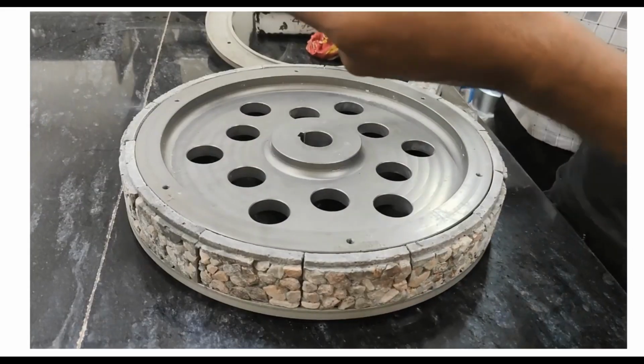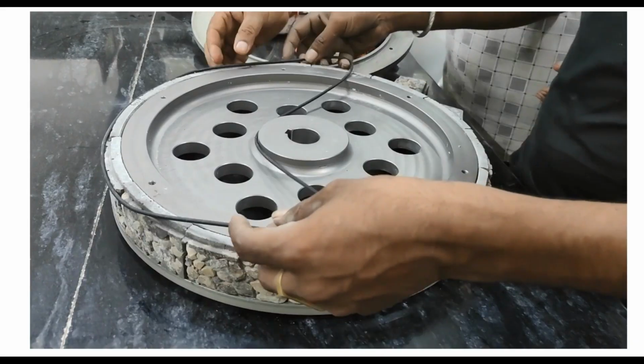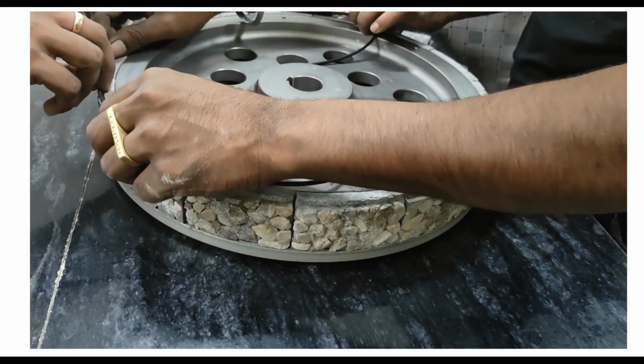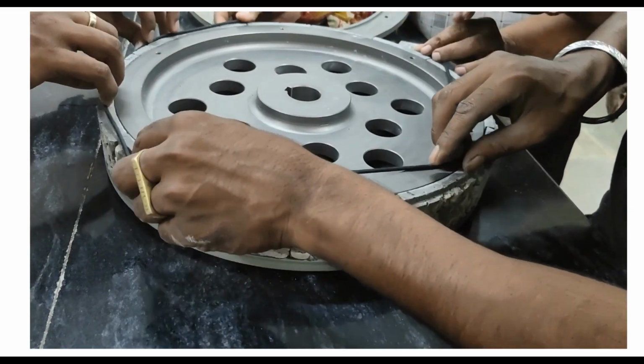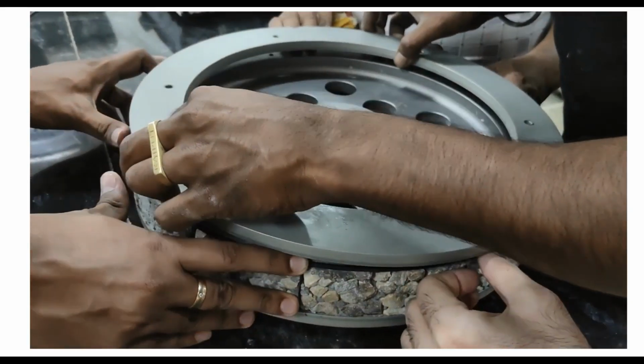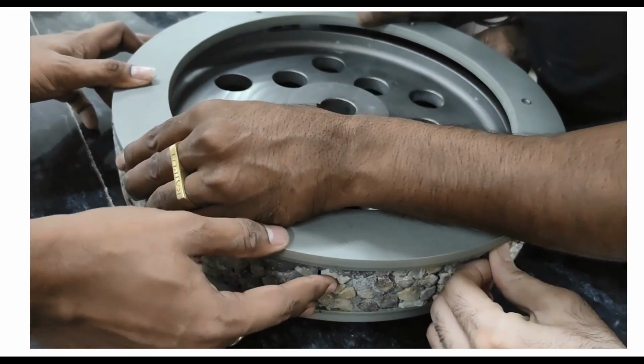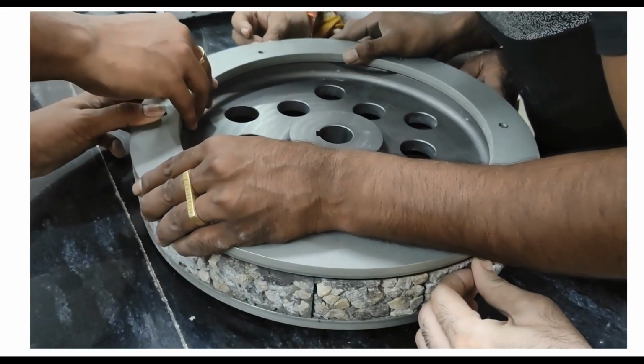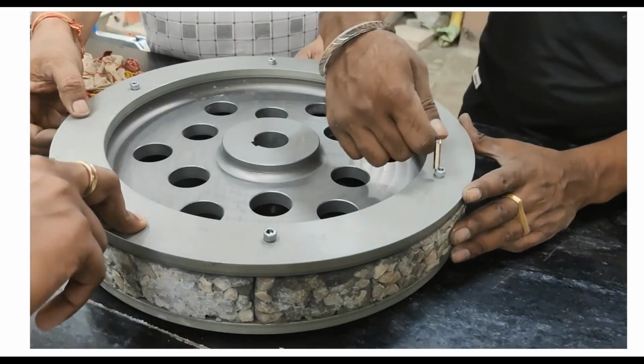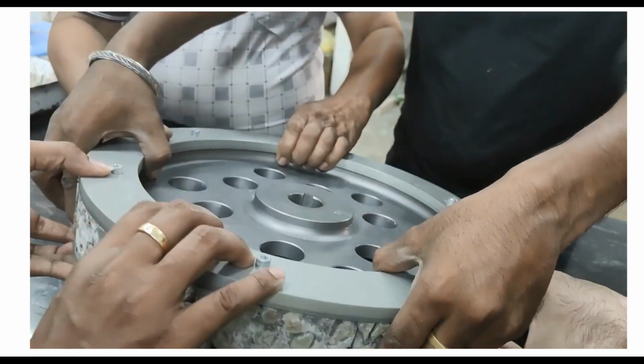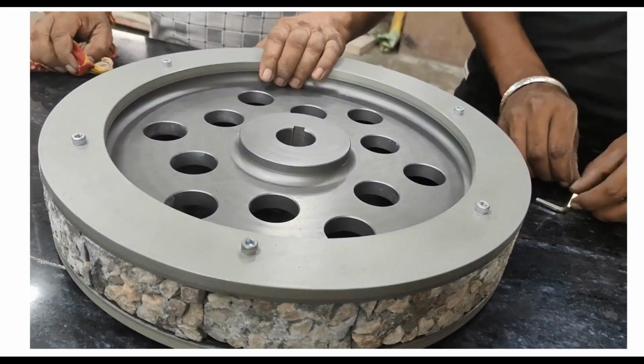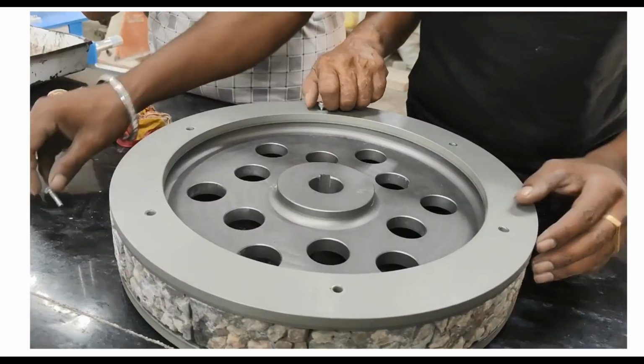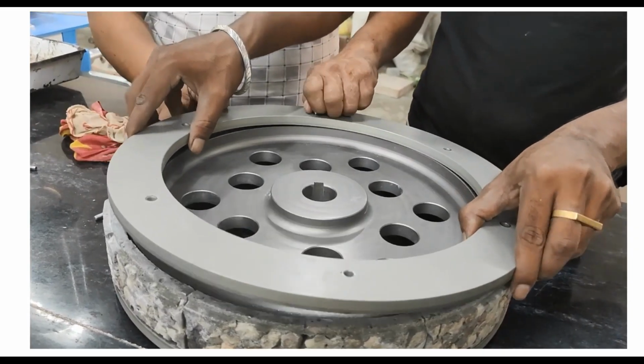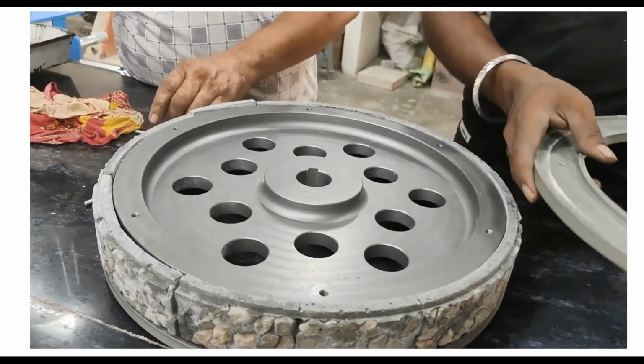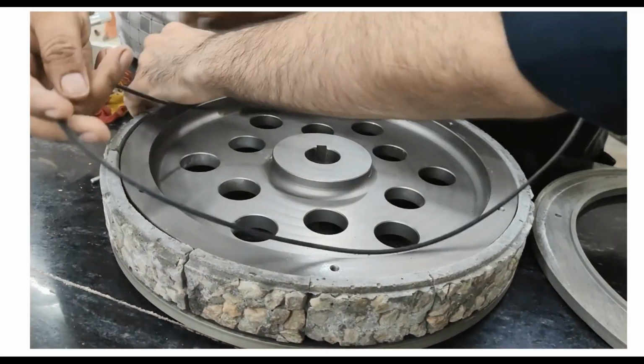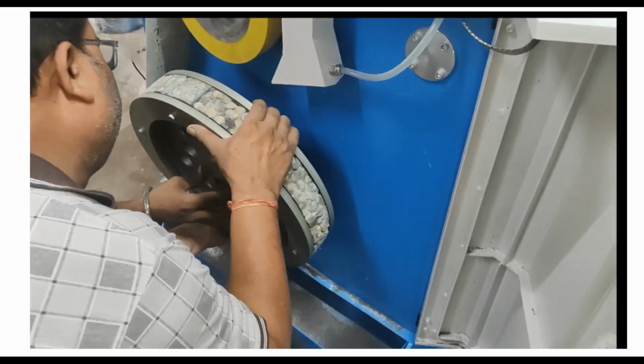then you place the rubber rings. This O-type rubber ring is used on each edge of the wheel to hold the specimen tightly. So you place this O-type ring on the specimens and then cover it with the metal ring. Now this wheel is to be reversed and remove the upper ring, place the second ring now here. This is rubber ring and tightly close.